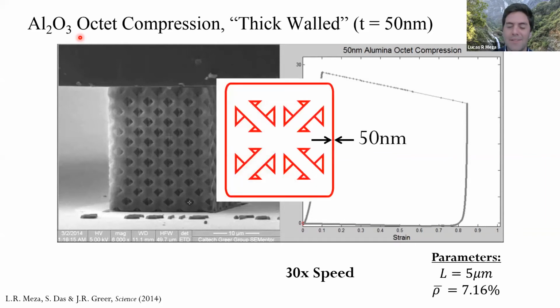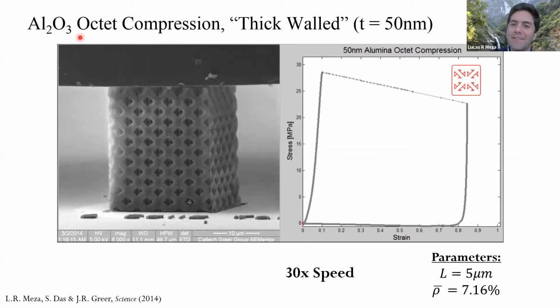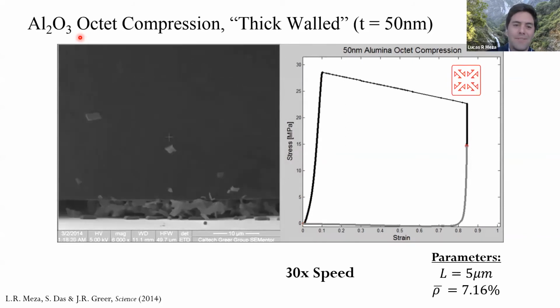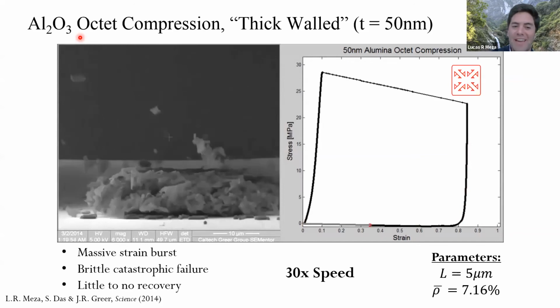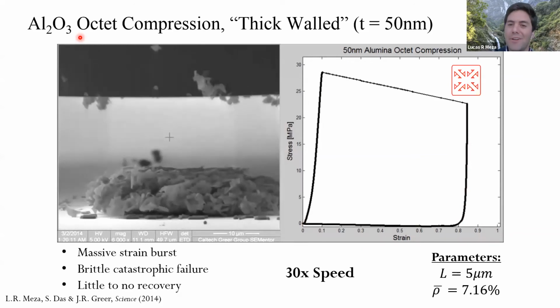So this, I'm going to say, is a thick-walled structure, thick here being 50 nanometers — that's the length scale we're working at as a frame of reference. In compression, we get reasonably high strength, reasonably stiff performance, but brittle, catastrophic failure — there's a single large strain burst, and the whole structure crushes.